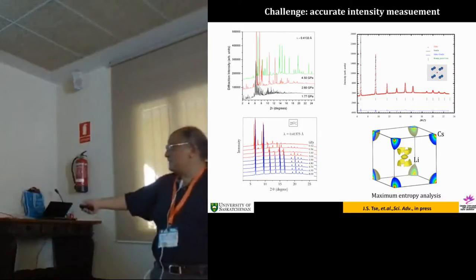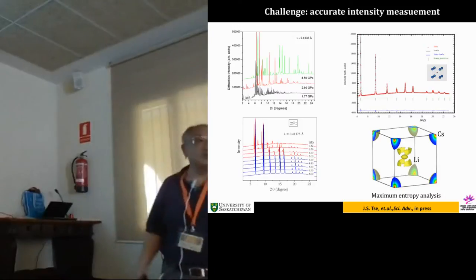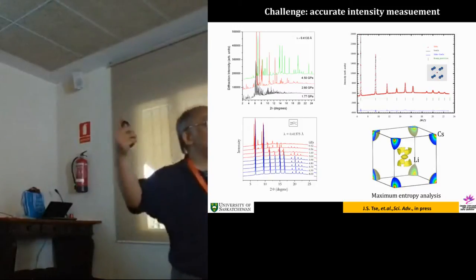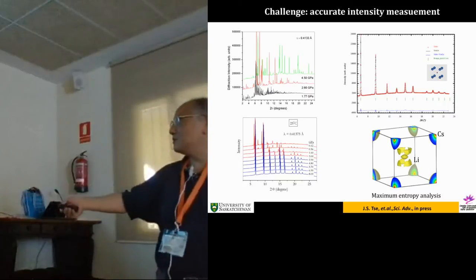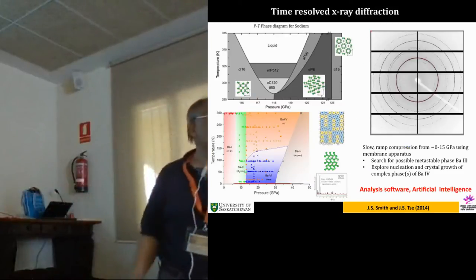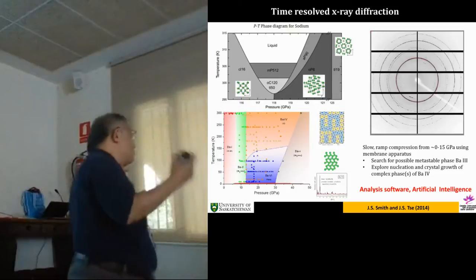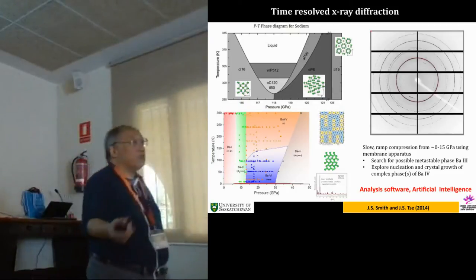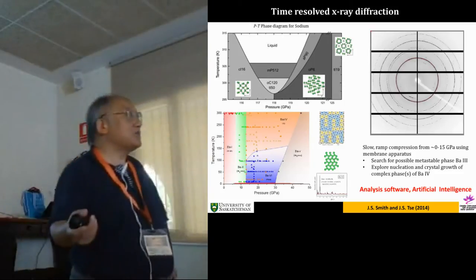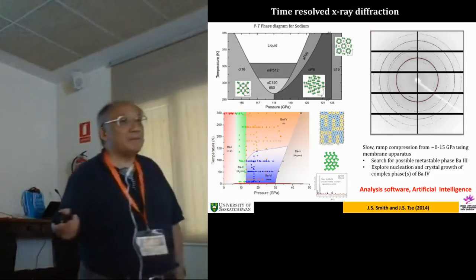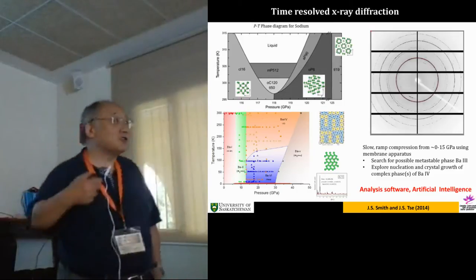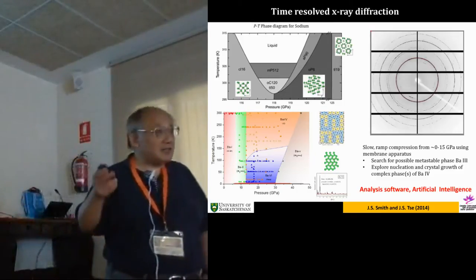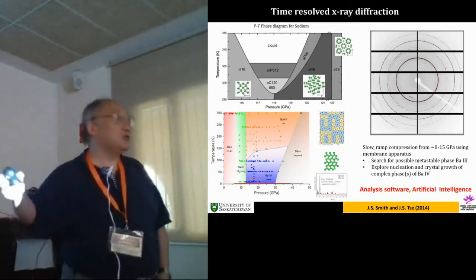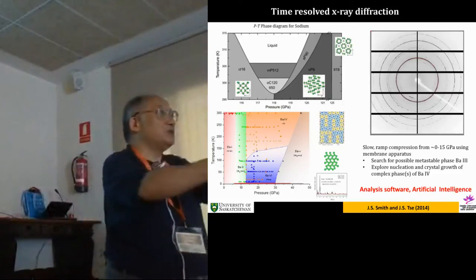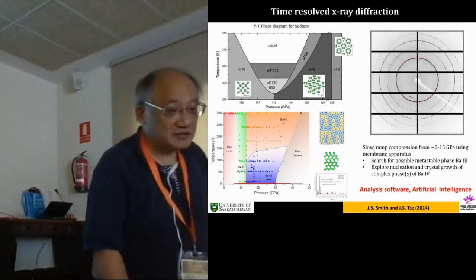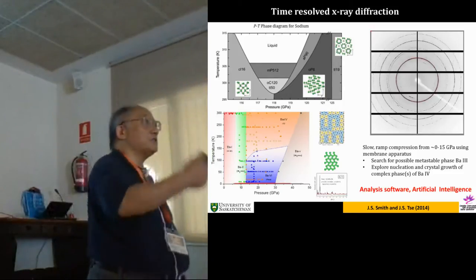It turns out that the cesium loses the electron to lithium, forming the p-loop here. So the electron actually moves from cesium to lithium at this pressure, very low pressure, around 10 GPa. Why the theoretical calculation doesn't predict it, I don't know. The property is a metastable state, and it's slightly non-stoichiometric. It's not exactly 1 to 1, it's 1 to 0.7, because we just put the metals together, we cannot really get a pure phase. But it's actually an easy, straightforward method.